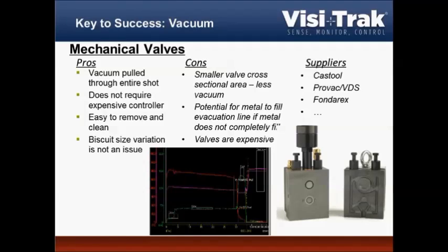The mechanical valves, I think everybody's familiar with the typical Castool or the VDS ProVac or Fondarex valves. The pros are vacuum is pulled through the entire shot. That's ideal. That's what we want. We don't need an expensive controller. It's relatively easy to remove and clean, and biscuit size variation is not an issue. So if your machine is not very precise, then that's a good way to go. The downside is typically smaller valve cross sections and the potential for metal to fill into the valve, and the valves are then also expensive, and it takes quite a bit of maintenance.